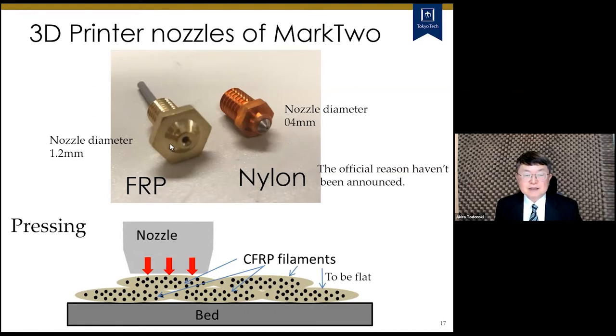And the other one is a nozzle to print continuous carbon fiber composite or glass fiber composite. And you can easily find that the diameter is very large. The nozzle diameter is 1.2. The official reason has not been announced why this nozzle has this large diameter. And by using this, this nozzle presses the CFRP filament to get a flat surface. So this configuration is very different from the conventional 3D printers.